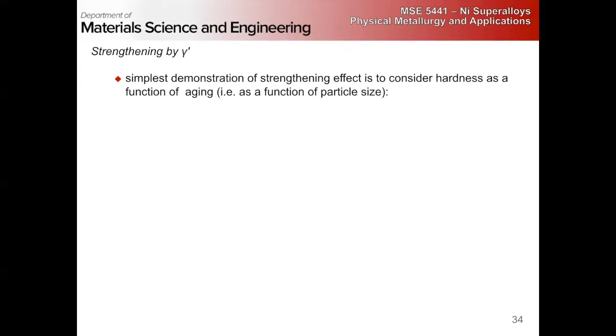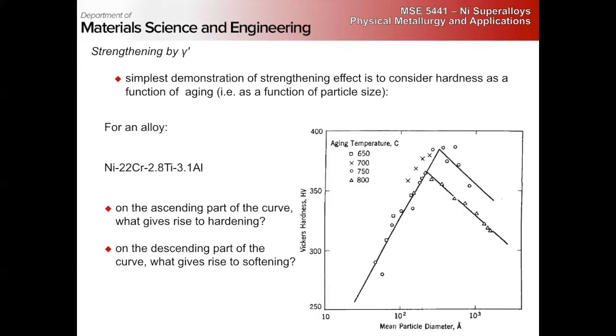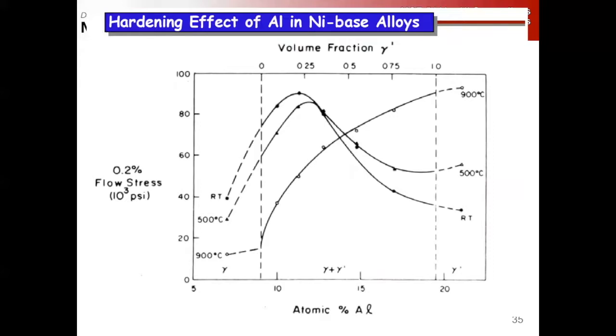In gamma prime, to a first assumption, we just think of it as we would any other precipitate, right? And so that means the strengthening effect for a given volume fraction of gamma prime is going to depend on the particle size, right? And this mirrors what we saw before, right? So you can think of this as being analogous to the cutting and looping curves, right? So that as we make the particles larger, they become more difficult to cut, but eventually for a given volume fraction, they become too far apart and it starts to become easier to loop, right? So something interesting happens.